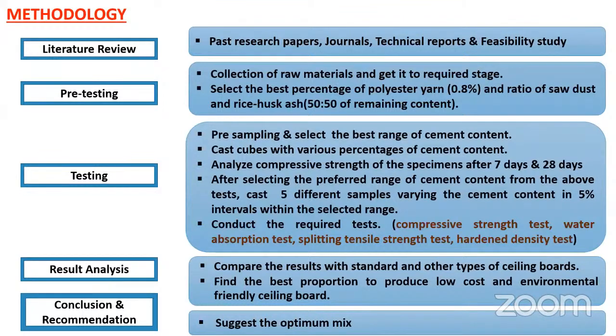After selecting the preferred range of cement content from the above test, cast 5 different samples varying the cement content in 5% intervals within the selected range. Conduct the required tests, then result analysis.